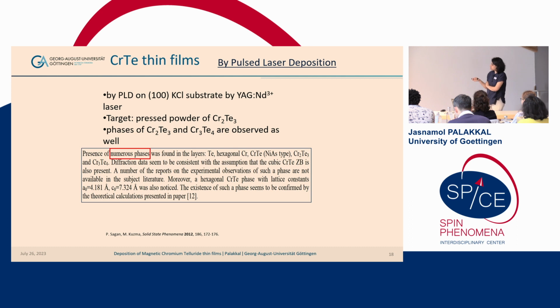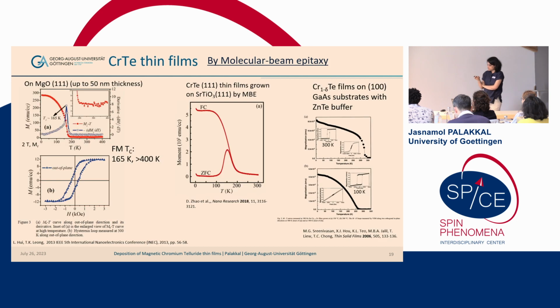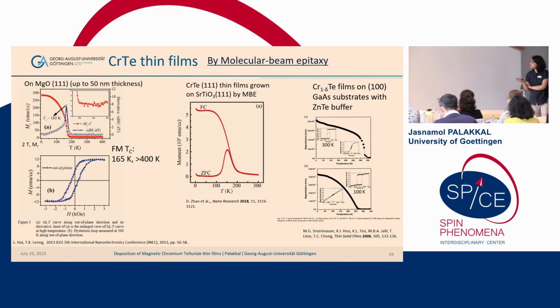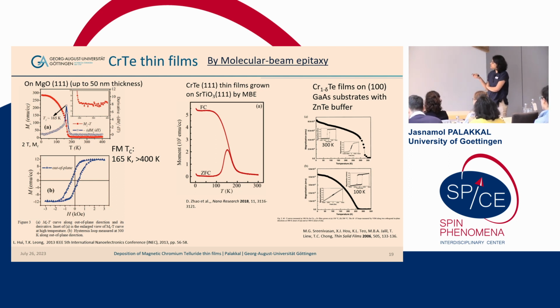So people started to grow this material by using pulsed laser deposition, by using a target of Cr2Te3, and they ended up in chromium telluride CrTe thin films, but they also found quite a lot of other phases of chromium and tellurium in their film. So as I said already, it's difficult to grow such materials by using a PLD, and people also reported chromium telluride thin film by using molecular beam epitaxy. So it's obvious that depending upon the deposition conditions or substrate or whatever, the material is showing different magnetic behavior.